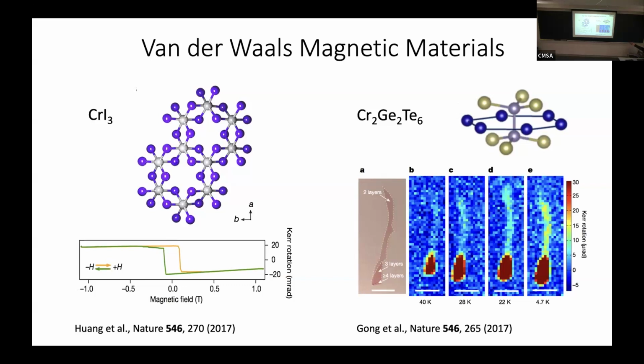It so happened I was working on chromium germanium telluride with Amir Yacoby at Harvard, doing experimental measurements using ferromagnetic resonance. And the issue I had is that the resonance of this material was outside the range of the equipment that I had. So I needed either better equipment, which was hard to come by, or a different material. And also this material is quite air sensitive. And so I needed to find a new 2D material that was magnetic.